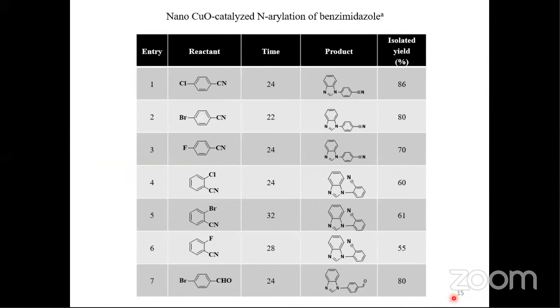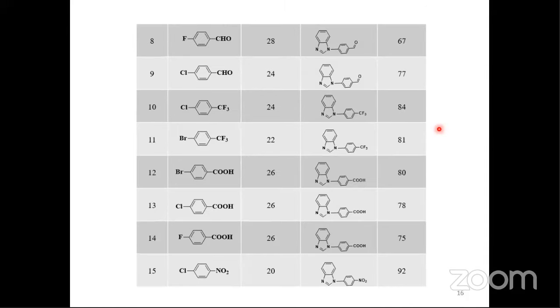Under the optimized conditions, the scope of the reaction is extended. It means that we have used different aryl halides. I told you we have used aryl fluoride, aryl bromide, aryl chloride with different substituents in different positions. The substituent in the para position, substituent in the ortho position, cyanide substituent, aldehyde substituent. You can see here the isolated yield of the product is moderate to good in almost all the cases. You see, different substituents were tried. It means that the catalyst is compatible. Whatever aryl halide you use, you can carry out the N-arylation process, and you can prepare different derivatives of N-arylated